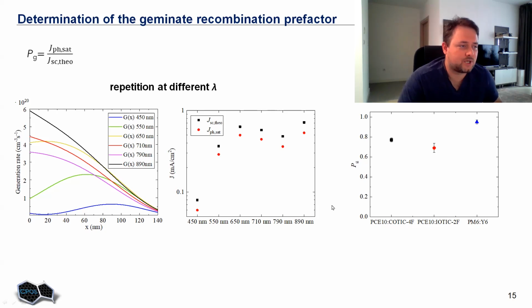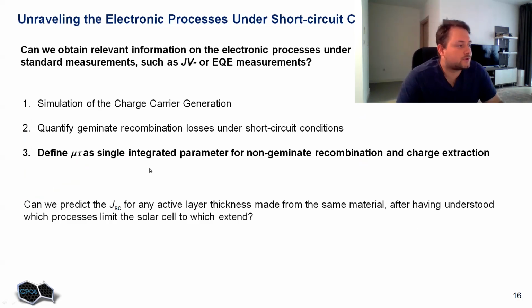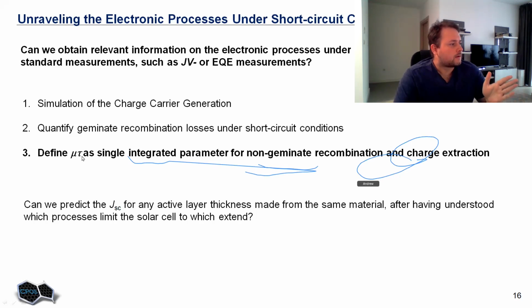Once we have this geminate recombination prefactor, we can proceed further and define a parameter which is called mu tau. Mu stands for mobility, tau stands for effective recombination lifetime. This single parameter, mu tau, quantifies non-geminate recombination losses and charge extraction. Because mobility obviously defines how fast we can extract charge carriers, and the effective recombination lifetime, in the case of multi-mechanism recombination dynamics in our solar cells, where we have bimolecular recombination, trap-assisted recombination in the bulk, and trap-assisted recombination at the interface between the active layer and electrodes, gives us an effective quantification of how many charge carriers we lose.